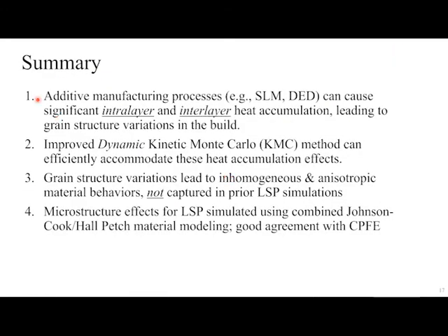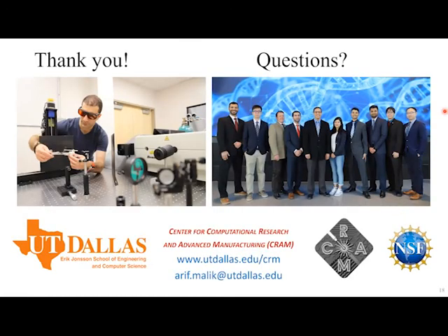So in summary, we know in additive manufacturing like SLM and DED, we can get significant intralayer and interlayer heat accumulation that leads to grain structure variations. So we improved upon the classic kinetic Monte Carlo method to capture the dynamic effects of the melt pool and heat affected zone. And we know that in the past in LSP modeling, the grain structures have not been captured, and we can do that now. And so in our simplified Johnson Cook Hall Petch material modeling approach, we show very good agreement with crystal plasticity finite element, but just a fraction of the runtime. And with that, thank you very much and I'll take any questions.